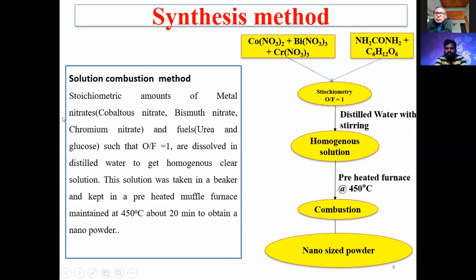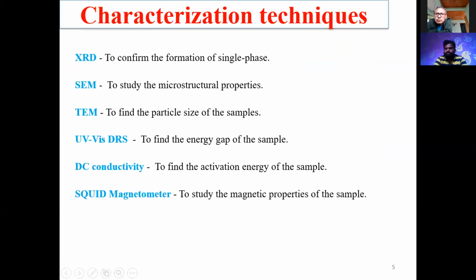The characterization techniques: XRD confirms the formation of a single phase structure, and we can also calculate the structural parameters of the samples. Scanning electron microscopy is used to understand the microstructural properties of the sample. Transmission electron microscopy is used to find the particle size of the samples. With the UV visible diffuse reflectance spectrometer, we can estimate the energy gap of the sample. From DC conductivity, we can calculate the activation energy of the sample. A magnetometer is used to study the magnetic properties of the sample.